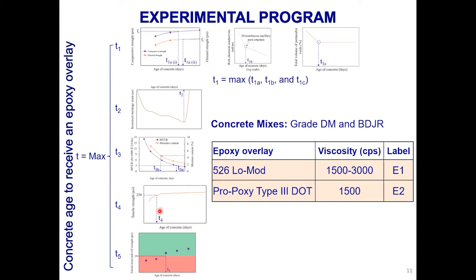In addition to that, concrete needs to have a certain tensile strength, and typically what we expect is more than 250. The reason for that is after we apply overlays, the performance is evaluated by conducting a direct pull-out strength test. So in that case, we want to have bond strength more than 250. So concrete needs to reach that strength before we apply overlays. So that's the fourth time parameter.